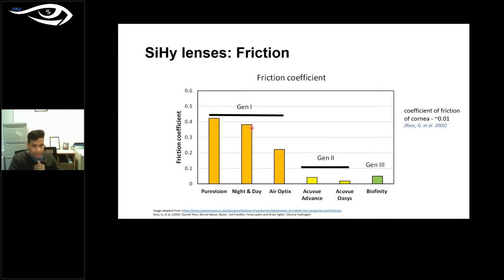And this particular chart here is coming from one of J&J's notes. They have given only numbers, but I have put that into a graph format so it'll be easy for us to understand. So friction coefficient, remember anything closer to 0 is good and anything closer to 1 is not so good. So look at the first generation contact lenses. They have a friction coefficient much closer to 1. Although Air Optix is slightly exceptional, you see that generation 1 is actually not so good. While we need a lens which is about 0.01, these lenses have a friction coefficient which is slightly higher. And you might notice that generation 2 and generation 3 lenses are relatively better in terms of friction coefficient.